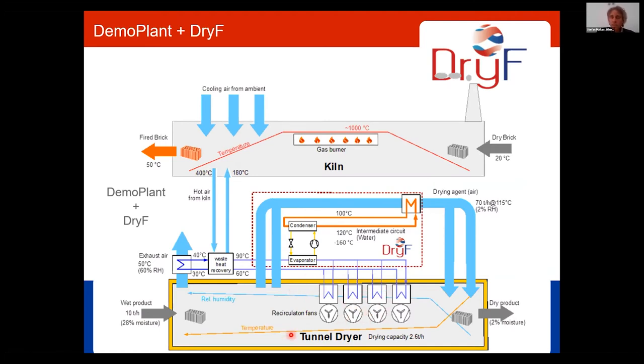But since this dryer building is limited in space, it's a decades old building, and it's not possible to reach the residual moisture needed to be ready for the kiln, we need a higher temperature. And this is where dry efficiency comes into this project. DryF picks a quite small part of the energy of the 90 degrees water circuit and lifts and provides temperatures of up to 160 degrees.